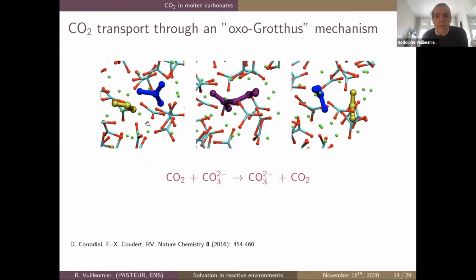And it diffuses through a kind of Grotthuss mechanism. It's like we have the acid CO2 in the base, like we have H3O+ in the base H2O, and it diffuses through an oxo-Grotthuss mechanism. There is an O2- transfer to CO2, forming this intermediate reminiscent of H5O2+ in water, and then the transfer is complete and we have a new CO2 that is formed, and the diffusion of CO2 goes through these hops of O2-.